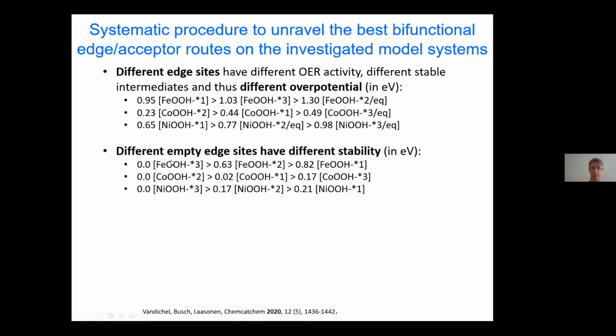So then we see that, for example, star three is more stable than star two and star one in case of iron. And in case of cobalt, we see that star two is more stable than the other one. But star two and star one are nearly equivalent. With nickel, we see that star three is actually the most stable one. And well, surprisingly, this results in the highest overpotential on this site.